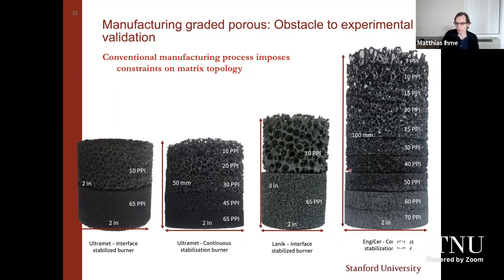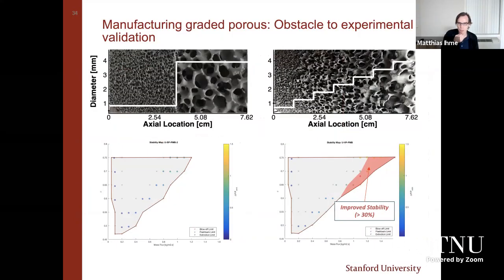You're seeing some gaps. You're seeing some cracks and fractures here. So this is certainly not necessarily the best design, but it turns out that we are already getting some indication that this concept works. So really consider this as an intermediate step. After I can show you the proof of concept, we want to look at some more advanced designs, right? So the improvement of this incremental profile over the step profile, illustrated here, is that yes, indeed, we are seeing improvements in the stability by about 30%. It's not a factor of 2, but it's already noticeable, and we're quite pleased that this initial concept is actually working for this design, right?